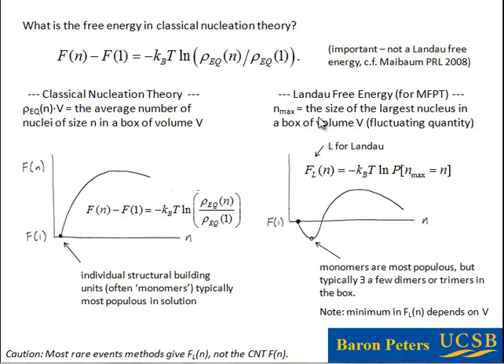It's important to recognize the difference between these two things. The classical nucleation theory definition deals with averages — the density of nuclei of size N divided by the density of nuclei of some reference size 1 — whereas the Landau free energy has to do with the largest nucleus in the simulation box at any given time, which is a fluctuating quantity. So even though monomers are still the most populous, they are not the minimum in the Landau free energy curve. Typically you have at least a dimer present, so the minimum occurs around size 2.